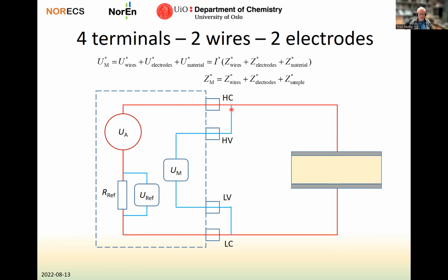Now, since there is no current going through the voltmeter, because the voltmeter has a very high impedance, we draw them in blue, and therefore there is no voltage drop here and here or here to the measured voltage. So now the measured voltage consists only of the voltage over the wires and over the electrodes and over the material. So now the measured impedance contains only the wires and the electrodes and the sample. So we have got rid of the terminal contact problem.